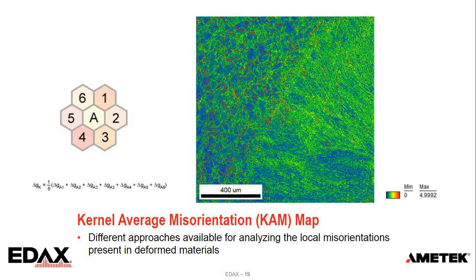Typically for regular EBSD, our precision is somewhere around 1/10 of a degree. When misorientations are higher than that, we can start looking at how those are distributed. We do this in one form of a map called a kernel average misorientation map, or a KAM map, where for every pixel in the map, we look at the misorientation between its 6 adjacent neighbors, take the average of that and color it accordingly.